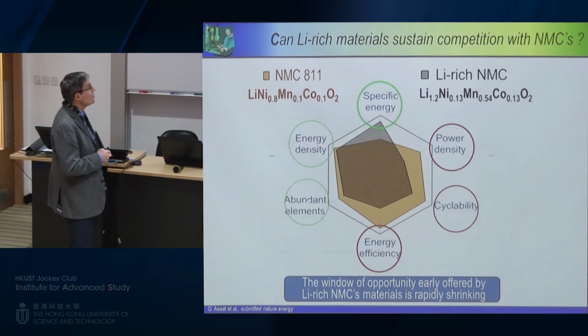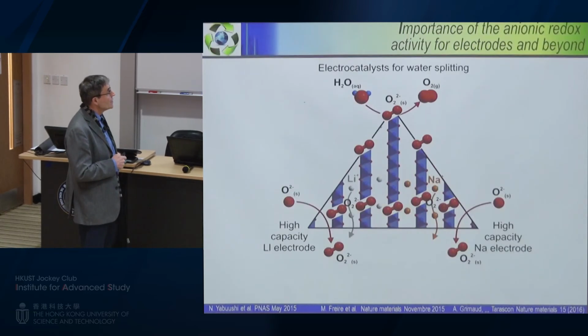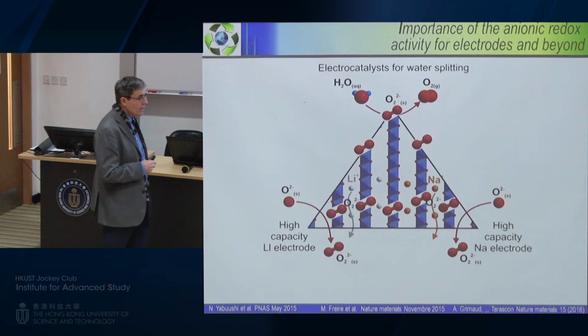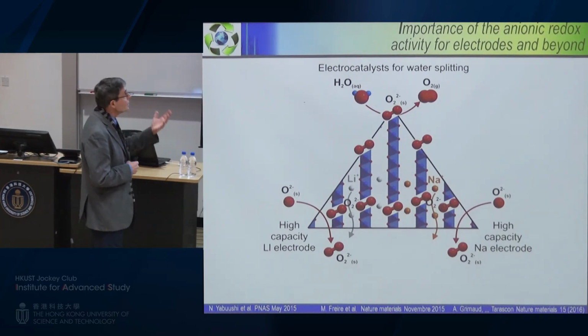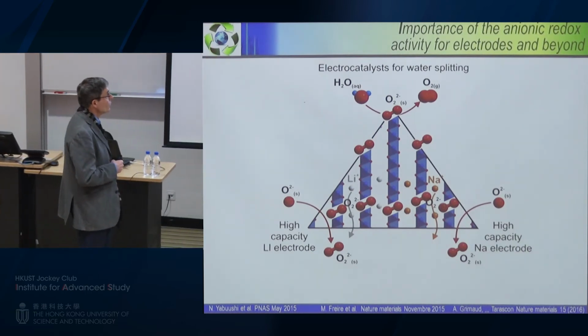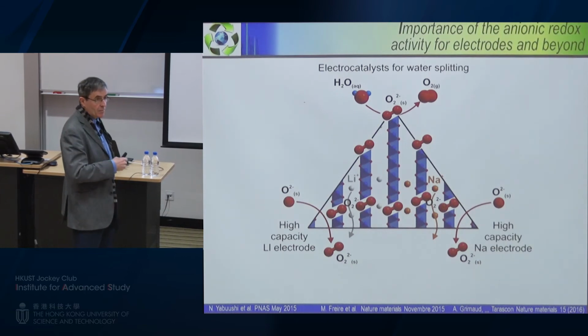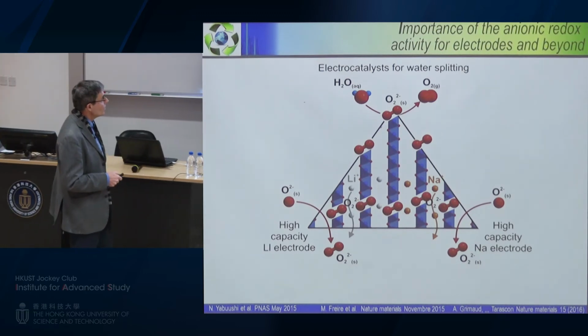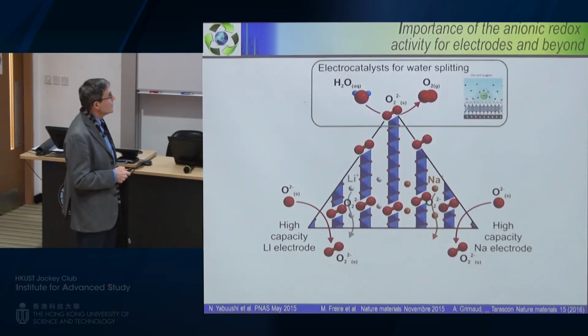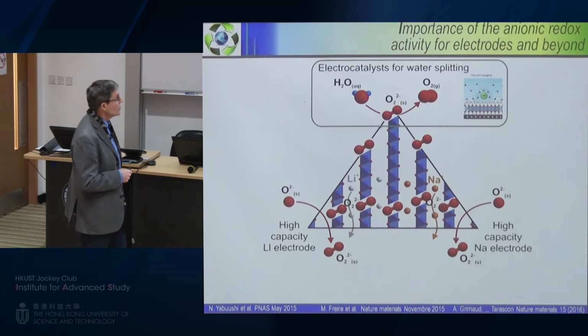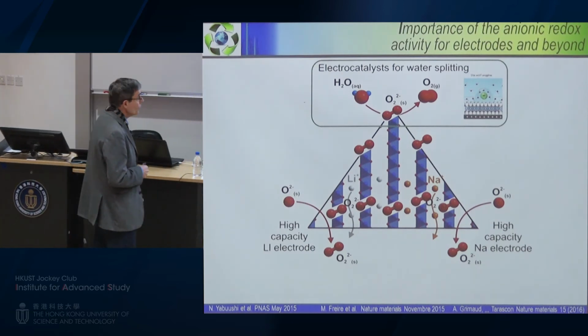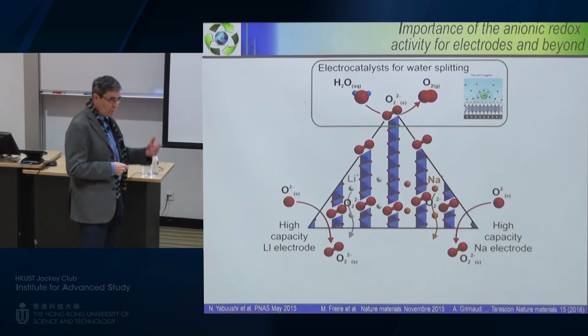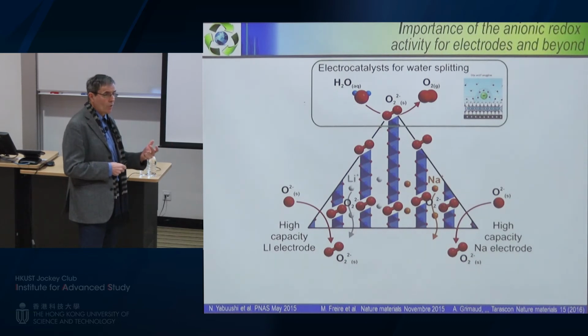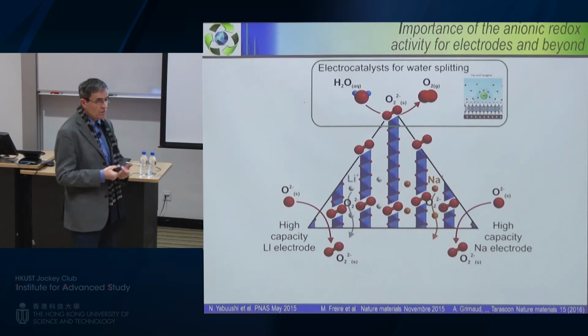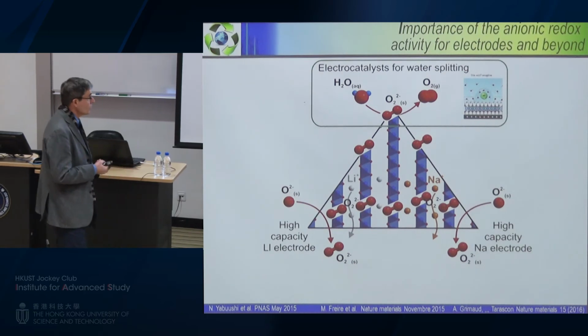So this, more or less, will conclude this first part, in which I told you what was the advantage of this paradigm, and what I want to show you now is that it has some advantages also beyond lithium-ion. Because you can see here, we can also have quite some advantages for water splitting, because now we can design materials in which we can monitor the amount of peroxo-like species, and this is quite interesting for oxygen evolution reaction and for water splitting.